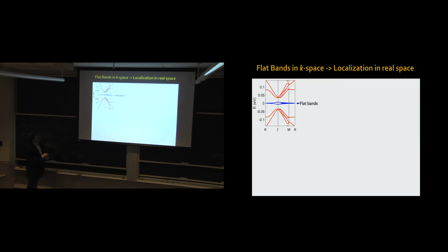Now, this is energy momentum, and this blue set of bands is these flat bands. Flat in momentum space - if you now do the Fourier transform to go back to real space, this means highly localized in real space. The Fourier transform of a flat thing is a delta function.